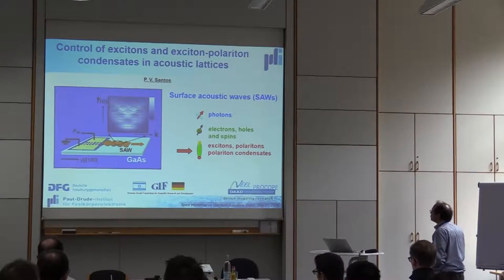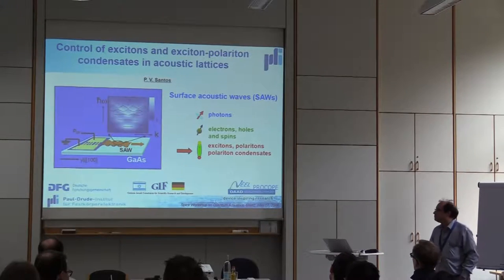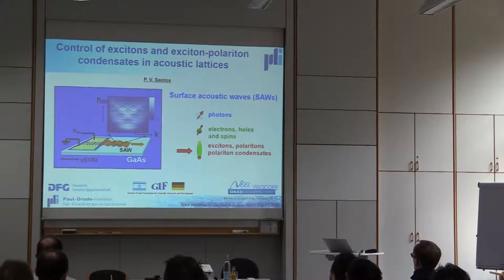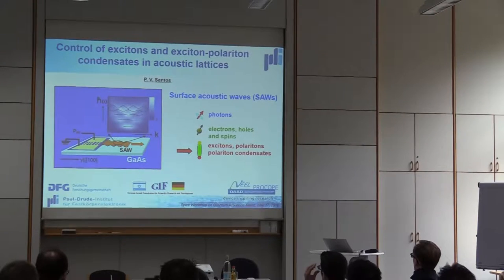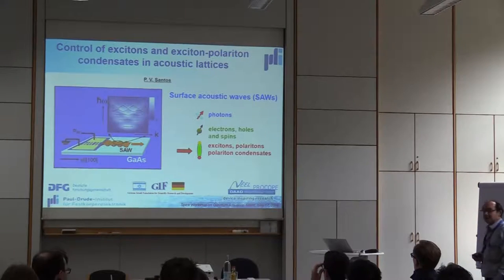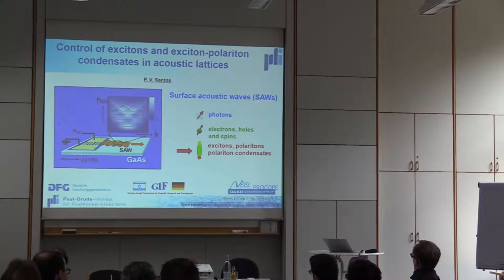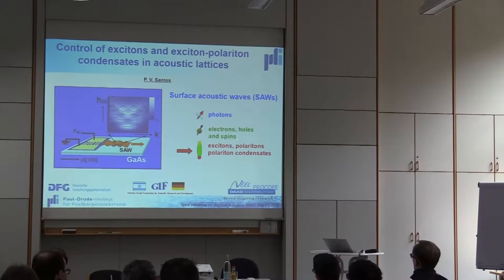What I'd like to do today is to review some recent results we have on the control of excitons and exciton polaritons using surface acoustic waves. Excitons are basically an electron-hole pair bound by the Coulomb interaction. Acoustic waves have very special properties that allow us to control excitons — they produce a moving strain field. Although excitons are neutral, these moving strain fields can confine and also transport excitons. This is going to be one motivation.